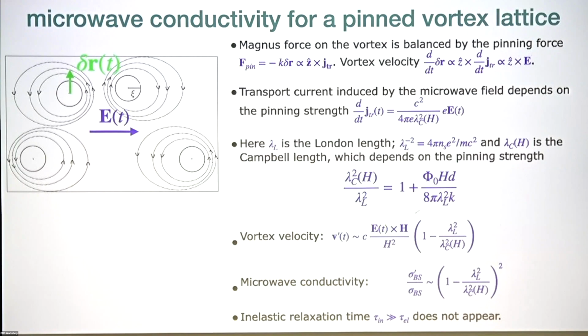Now at low frequencies, the Magnus force is not balanced by the friction, but primarily by the pinning force. And therefore, we can say that the displacements of the vortices are proportional to the transport current, which induces the Magnus force. Then if you take the time derivative of this relation, what you find is that the velocity of the vortex is proportional to the time derivative of the transport current, which itself is proportional to the electric field. So you still have the same result, that velocity is proportional to E, but the coefficient is different.